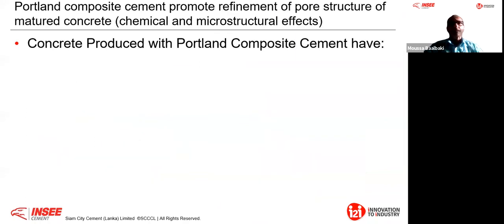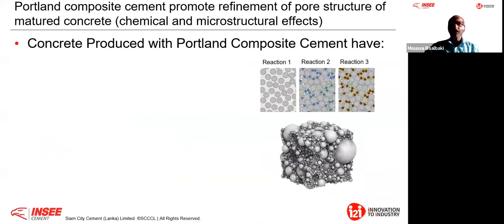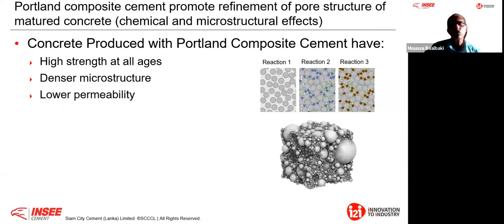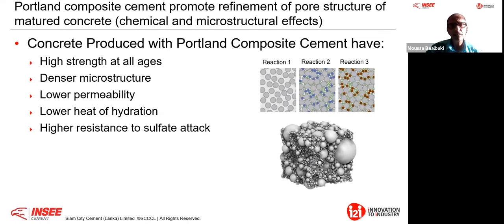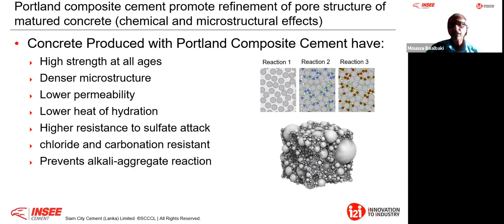Okay. Therefore, by using this Portland composite cement with a triple reaction, as I explained, you have really high strength at all ages. You have denser microstructure, low permeability, lower heat of hydration because the clinker factor gets reduced. High resistance to sulfate, as we explained, to chloride, to carbonation, and it prevents alkali aggregate reaction. And last but not least, the leaching. That is very important. Why do I say leaching?